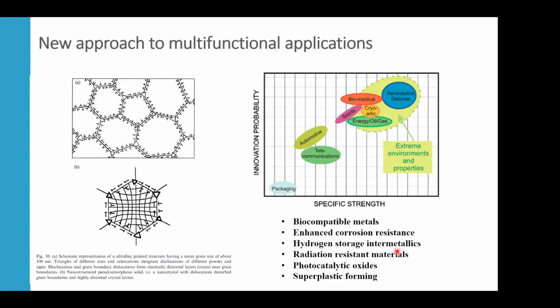And it's not only that the grains are small, but that the average width of the grain boundary is thicker, that the defect concentration in the boundaries is higher than in conventional materials. So there's a lot of free volume, or there's more free volume within grain boundaries. And that also increases, for example, diffusion activity, and changes the nature not only of mechanical properties, but also some other functional properties that are driven by grain boundaries.